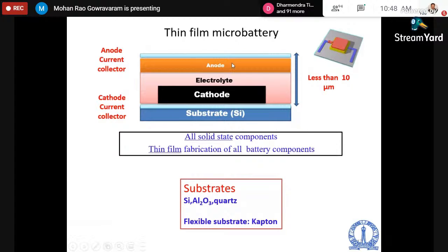So this is what it is. You have a substrate, which was originally thought to be silicon because they wanted to make it for microelectronic devices. Then you deposit a current collector, and then you have a cathode layer, that is lithium cobalt oxide. Then an electrolyte layer is built onto this, that is your LiPON, and then there is an anode layer, and then a current collector. As I said, the entire thickness of this battery is less than 10 micrometers, whereas your silicon substrate is not less than 250 micron thickness. Now it could be fabricated in any shape, size, etc. You could use any substrate: silicon, alumina, quartz, polyester, Kapton, whatnot. Anything could be used.